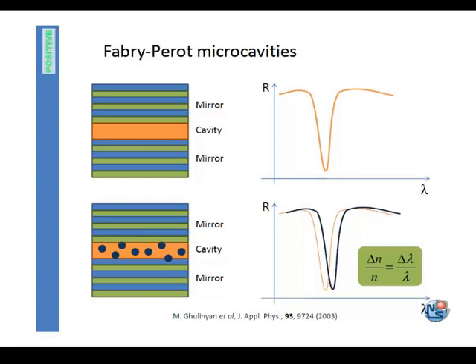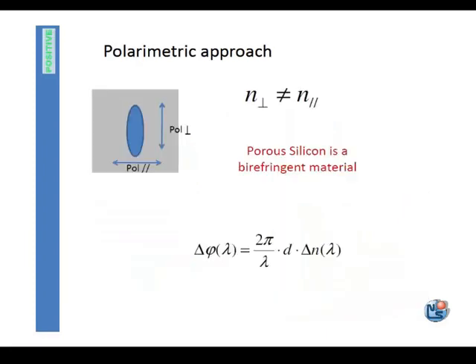But there's a problem. We can make very highly sensitive sensors with this approach, but if you want to make a point-of-care detection system, that means a robust and compact device where the doctor pushes a button and waits just for the answer of the analysis, this approach requires a careful optical alignment system, and it's hard to implement this in a robust device. So we changed our approach. We looked at polarimetry. Now, if you consider an elliptical pore, then horizontally and vertically polarized light feel a different structure. That means that the refractive indices for the horizontal and the vertical polarization will be different.